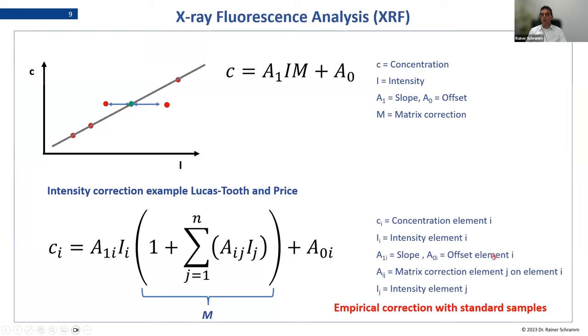And this is also a very important fact, that if you do such a matrix correction, your set of standard materials has to represent this effect. So you need some samples without matrix effect, and you need others which show extremely that effect, so that the mathematics are able to calculate these correction factors to do then the matrix correction for your application.